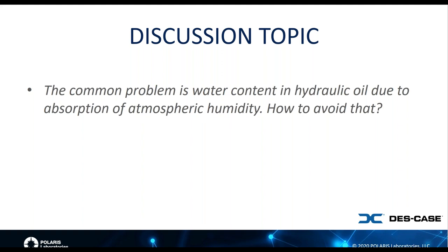You know, all oils, hydraulic fluids being no exception, are hygroscopic. So if you leave them in a high humidity environment, they would naturally adsorb moisture. And this is particularly true where the atmosphere is humid. There is a physical law called Henry's law, which basically says that the relative humidity of the water in air above an oil will be in direct correlation with the relative humidity of the water dissolved in the oil. So as an example, if the relative humidity in the ambient air is 80%, if you leave the oil sitting there, the oil will migrate and become 80% saturated with moisture.